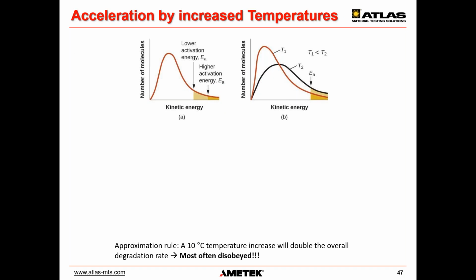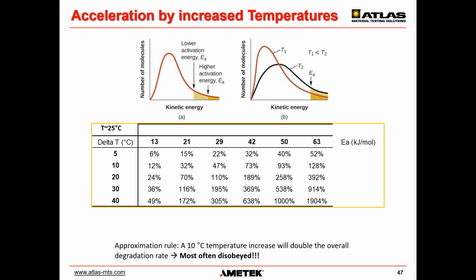Here you have this distribution. All but purely photolytic or photon-dependent reaction rates increase with temperature. The activation energy is a material-dependent property. It is the amount of energy that must be put, I mentioned that already, to overcome this barrier. And with a high activation energy, not many molecules have enough energy to react. If the activation energy is lower, then you have a bigger portion of molecules that have enough kinetic energy. And then if you change the temperature here, you can actually influence that a lot. This is a new temperature distribution for a higher temperature T2.